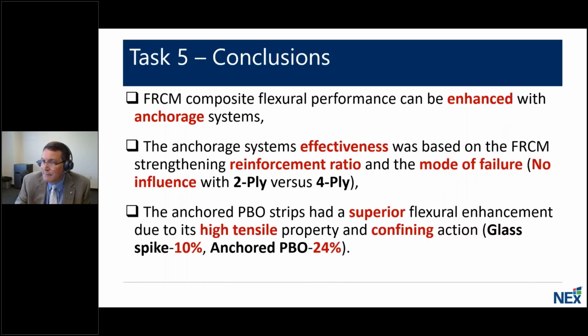So our takeaways for this last final task are, again, that the anchored systems are effective depending on the failure mode, but also on the reinforcement ratio, and most importantly, the mode of failure. No influence with the 2-ply system where we had fiber slippage failure, but very effective for the 4-ply system. In terms of enhancement, using the glass spike anchor with 4 plies, it was a 10% increase in enhancement. And for the anchored PBO system, it was an additional 24% enhancement using that system.